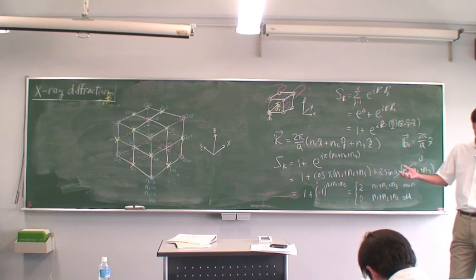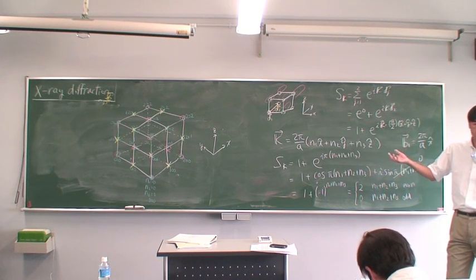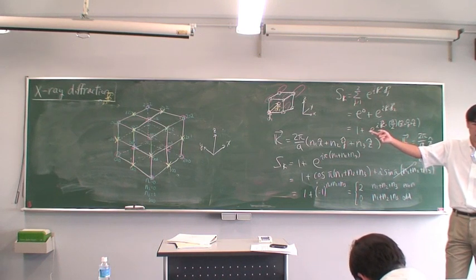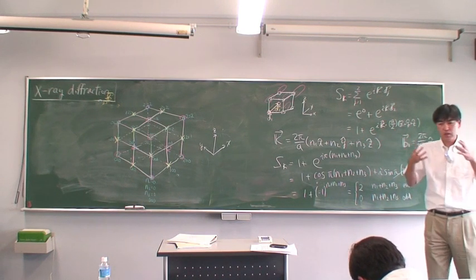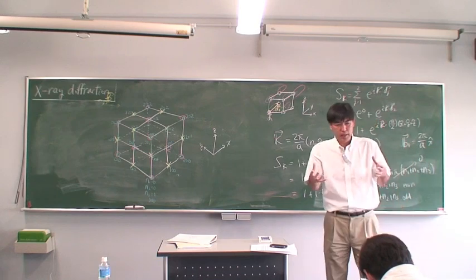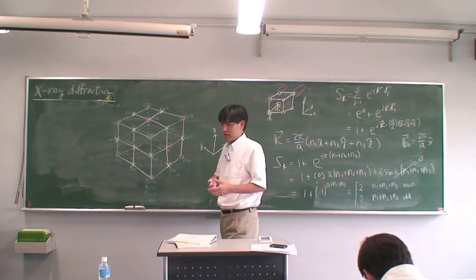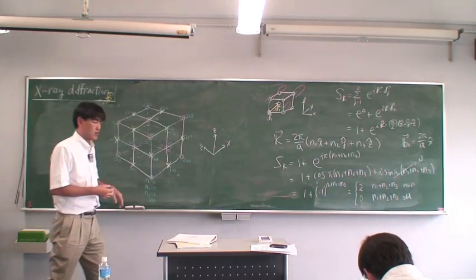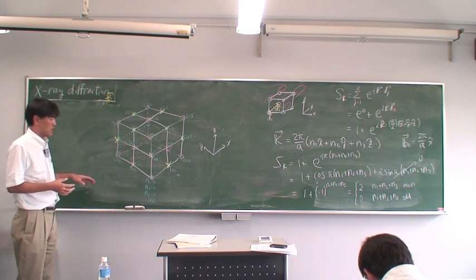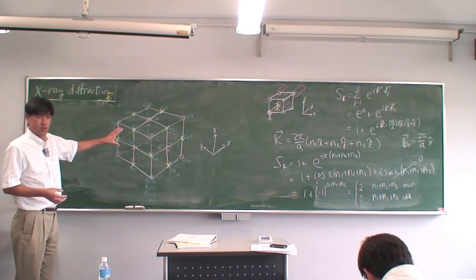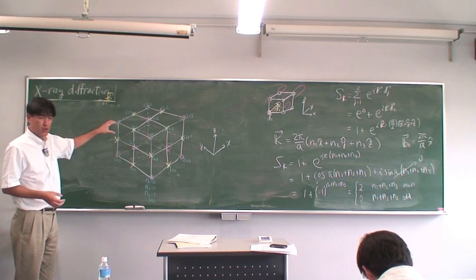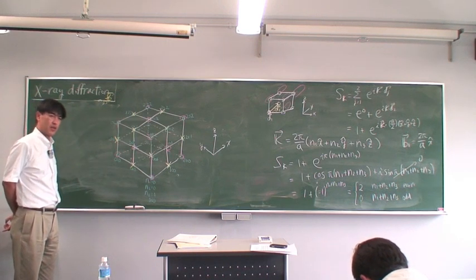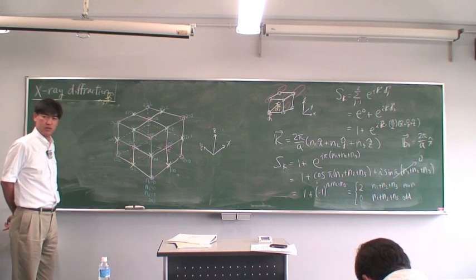I say this again: the reciprocal lattice of body-centered cubic is face-centered cubic. Even if we consider body-centered cubic as a cubic lattice with 2 bases, and go through all the structure factor calculation and so on, physics is always the same. At the end, we get face-centered cubic as the reciprocal lattice of the body-centered cubic.